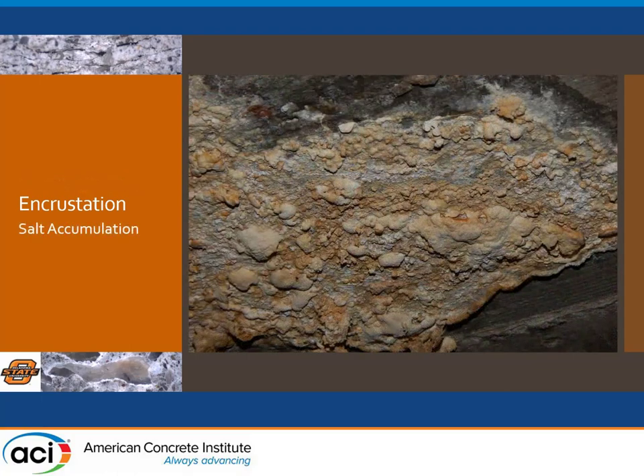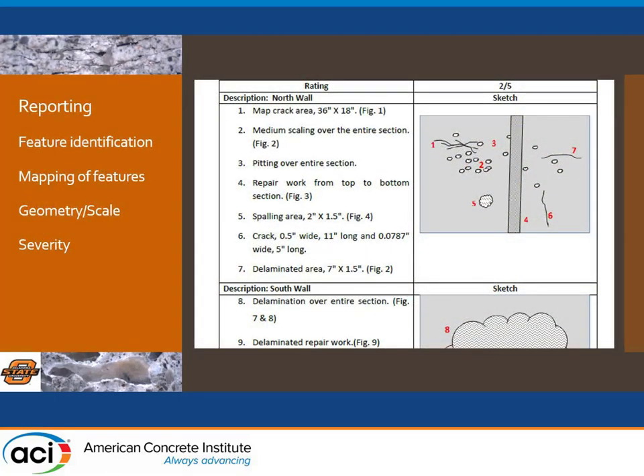We took a lot of samples. I had no idea what this was at first — we called it encrustation, but it really looked like zombie concrete. Very hard material, different colors. We took samples and did chemical analysis through X-ray fluorescence (XRF) just to get the elements. We did not do XRD to get the actual compounds, but we found high concentrations of sulfur, magnesium, calcium, chloride, and sodium.